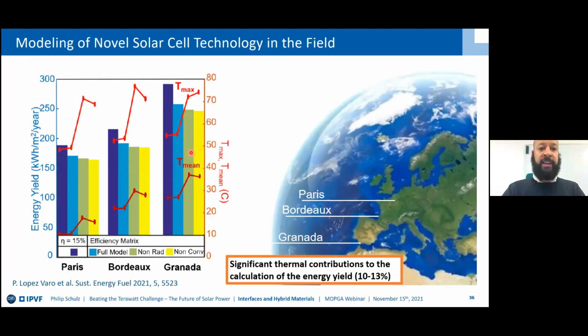She went a step further and evaluated this for different locations of deployment, from Paris to Granada. So we stay in Europe, but cover quite some geographical spaces. And now the real difference is here between this purple bluish curve, the energy yield, versus these curves where the thermal module has been applied. And you can see that the energy yield under realistic conditions is actually smaller than what you would expect at first. And it's important to keep these kinds of things in mind when we put a new technology on the market, to understand what is the expected outcome, and also then improve the modules on an individual basis.